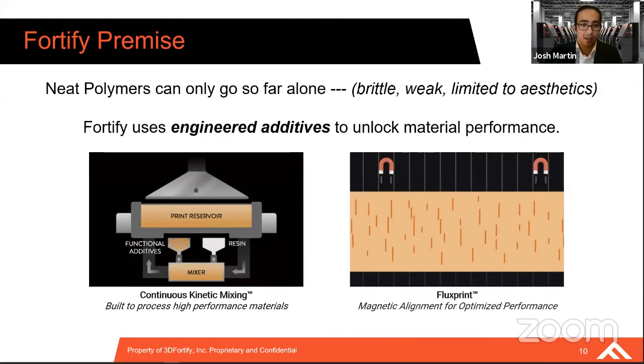In this case, there are two main components to our platform. The first is this continuous kinetic mixing, which allows us to mix these functional additives with high performance resins onboard the system. A lot of these material combinations are very viscous. They require being printed at high temperatures or even unique atmospheres, whether it's an inert atmosphere or under pressure. And this system allows us to handle those materials.